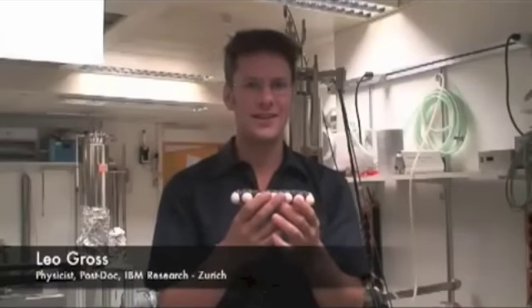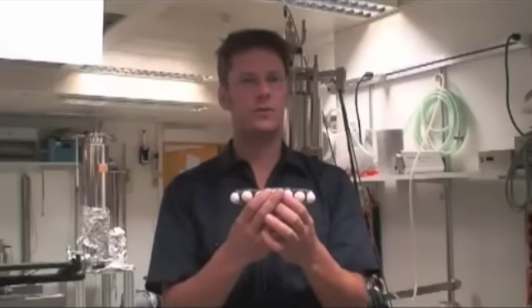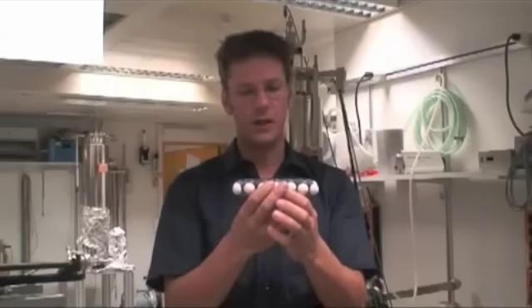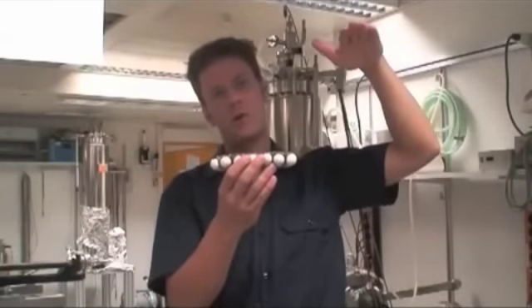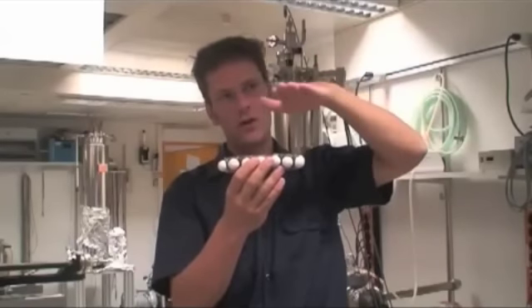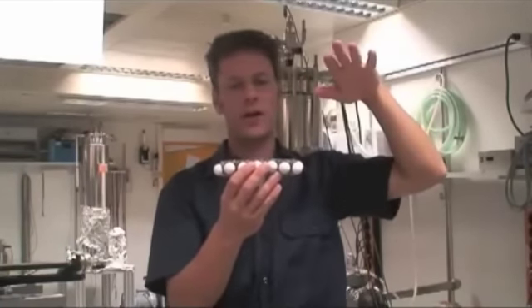The calculations helped us to understand what is the origin of the contrast that we observe in the experiment. And I'll try to explain this in brief. First we image the molecule far away. Then we see attraction by van der Waals forces and this attractive part has no atomic corrugation.